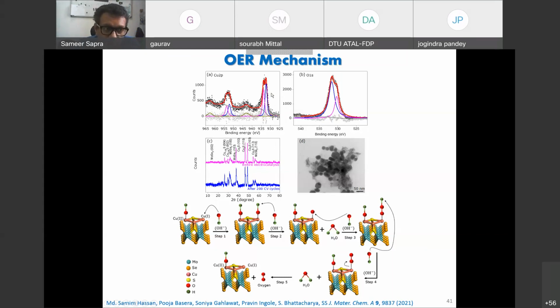So based on all these results, we proposed the mechanism over here, which was shown earlier, that you have some copper 2 sites and copper 1 sites. And then OH minus goes and attacks the copper 1 site, which is free. So both of these sites are now copper with OH. And another OH comes and attacks, okay, and takes out this H plus. So now you have copper with O. Another OH comes and attacks, and it forms an OO bond, OOH, the peroxide. And then, since this peroxide is there, we can get rid of this H plus using another OH minus, and then you have O2. Okay, when this O2 dissociates and free oxygen is released, copper 1 comes back to its state.